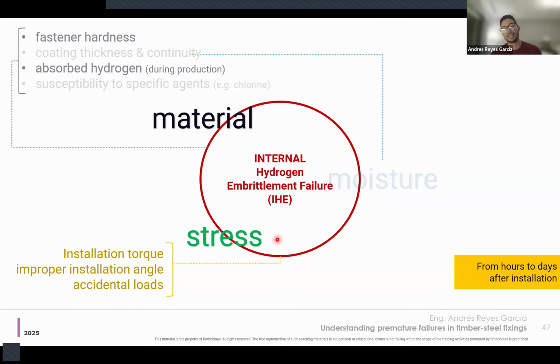How do we recognize it? It generally happens from hours to days after installation. This is very critical, because it happens mostly in dry conditions, so we don't have the effect of moisture, and it happens very early. And most important, this is the responsibility of the manufacturer. If this happens, and if we are providing the screws and it's proven to be internal hydrogen embrittlement, this is on us.